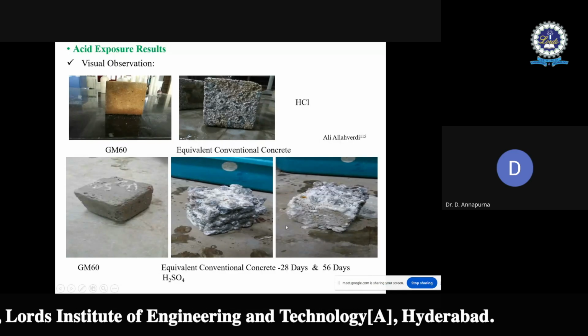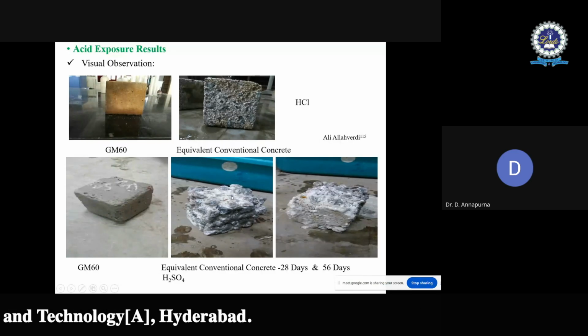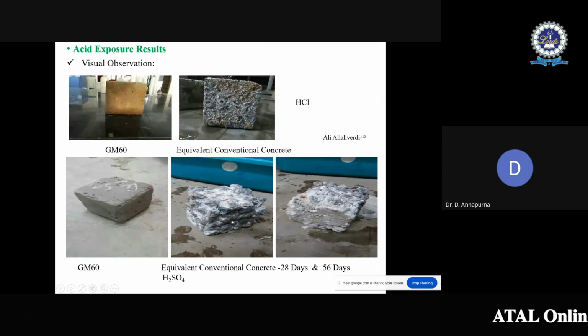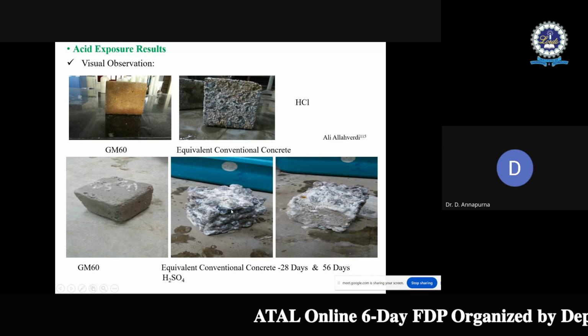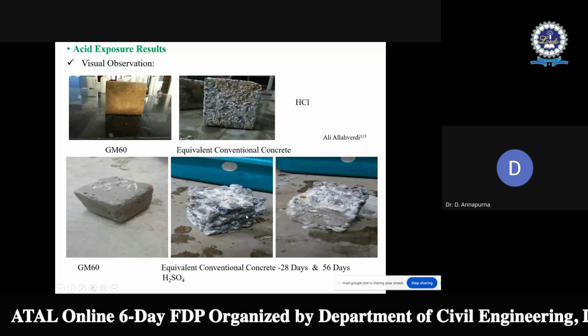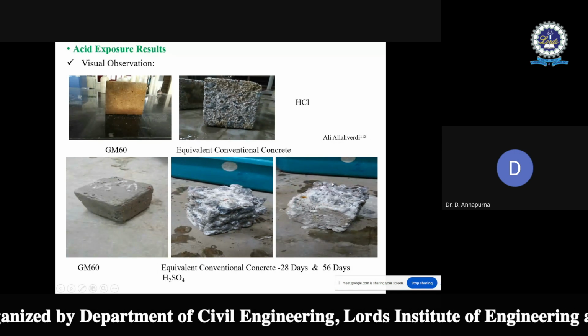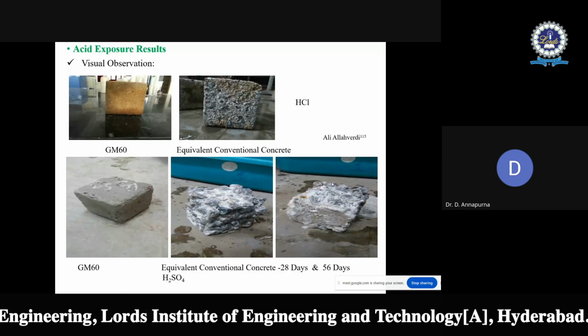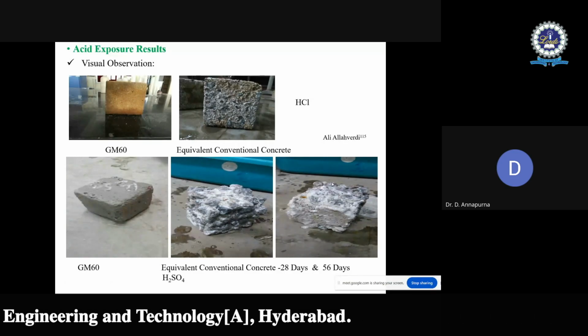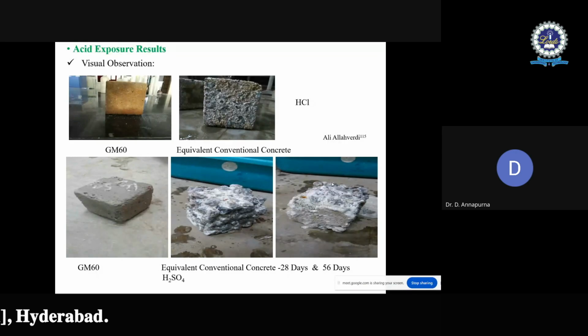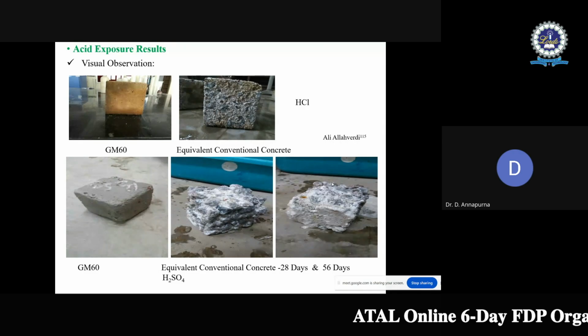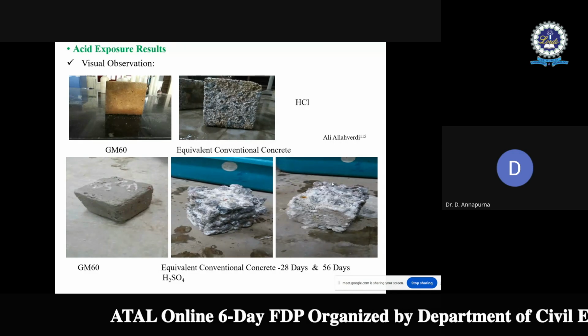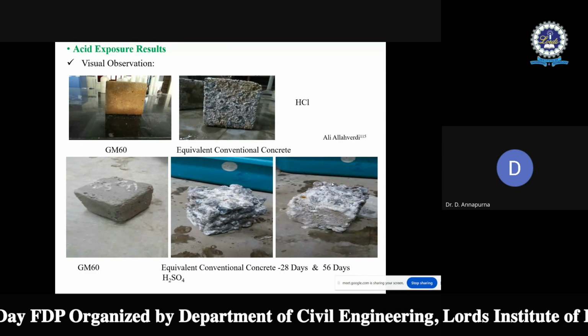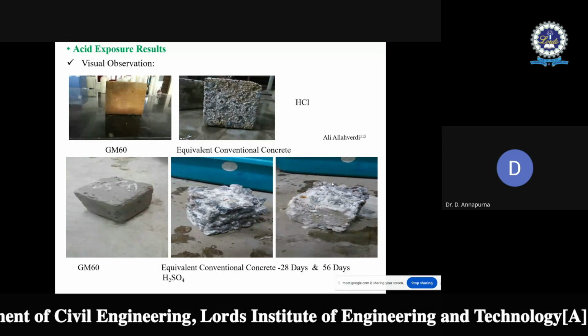But when it comes to the equivalent conventional concrete, how the sulfuric acid affects it is seen through these pics, when it is immersed in solution for 28 days and 56 days. After 56 days, a greater amount of degradation of the sample has occurred, with more softening of material. It is not possible even to handle that particular concrete. That is the reason the samples were taken out after 56 days only. After 180 days, the test is not conducted.